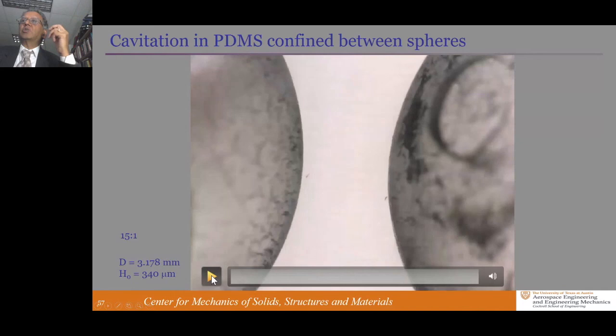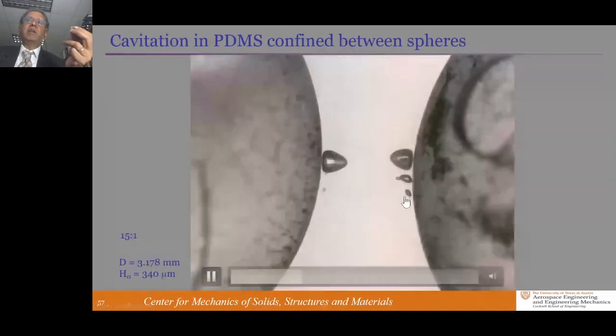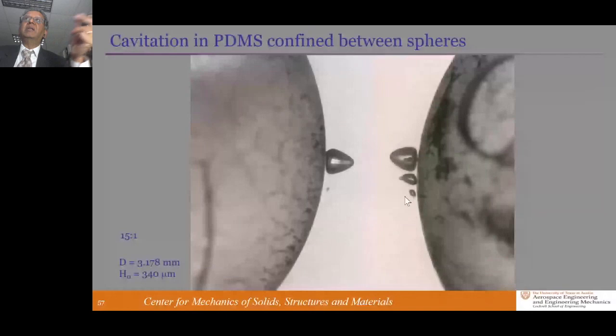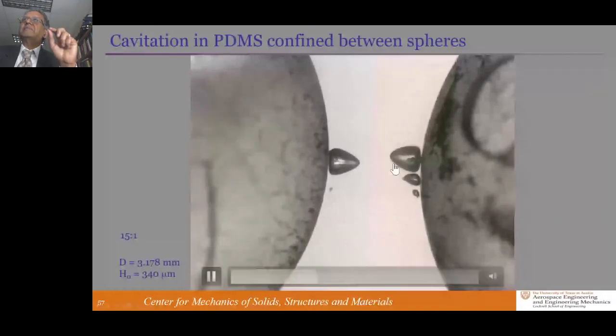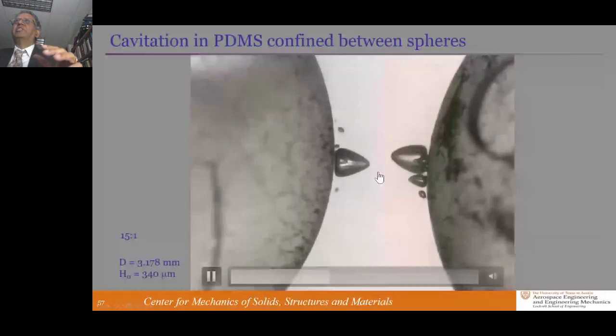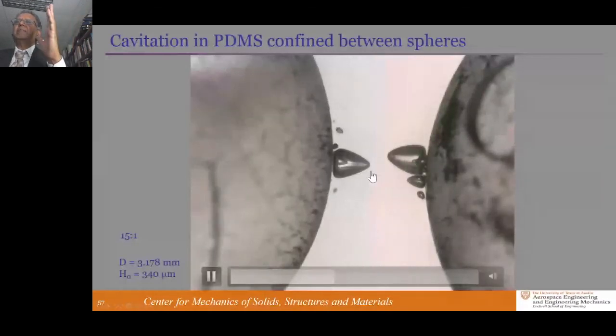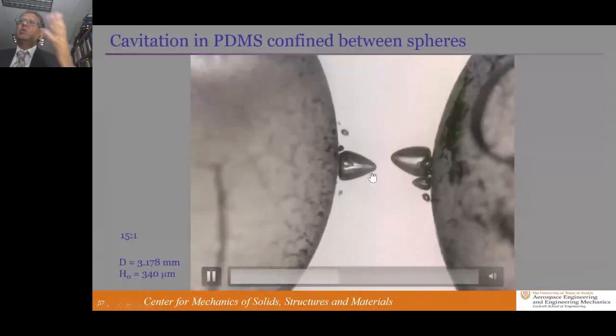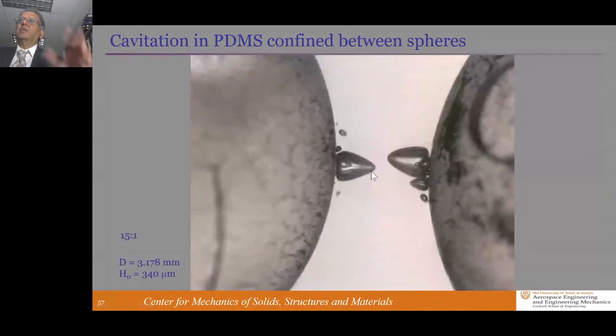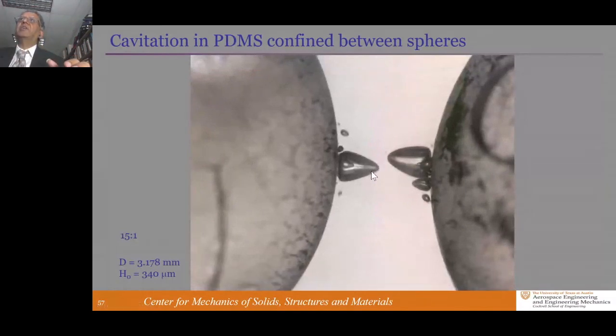And you can see there's a stochasticity to this. There are different nuclei that get popped up at different time instants, meaning at different global or local stretch levels. And they don't interact with each other. They don't coalesce. Some of them have grown to very large extents. And you could very easily visualize that these are penny-shaped cracks that if you unload them, they will go back and coalesce with each other. The two surfaces will go back to each other. All right.